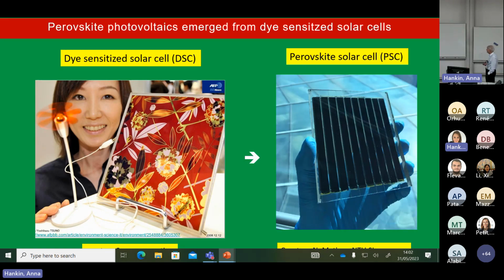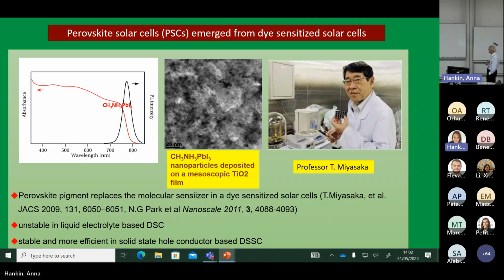photovoltaics. And so they evolved from dye-sensitized cells with the first study by Miyasaka, who just used the quantum dots of the perovskite methyl ammonium lead iodide. That was the first paper published, but these materials were very unstable. And so they dissolved in electrolytes. So for a while, nothing happened. Nothing happened. And only 3 years later, the studies were published almost simultaneously on a solid state version of the